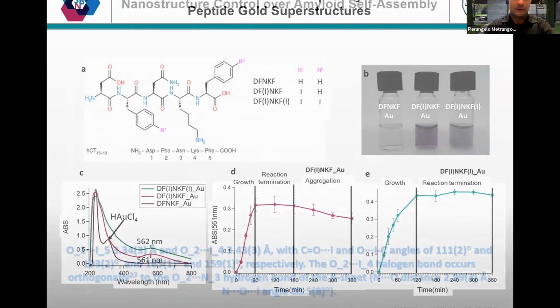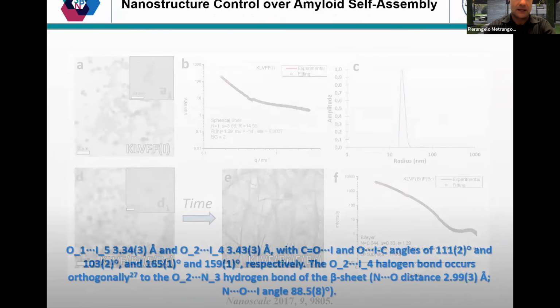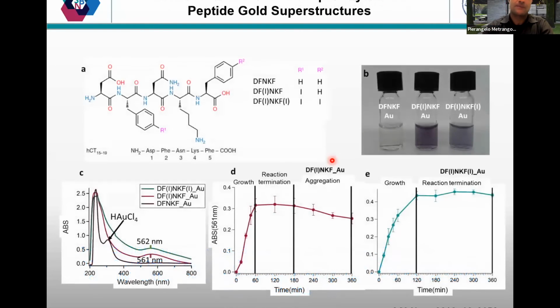Moreover, unfortunately here, for some reason, the crystal structure is not displaying, but in this paper we were lucky enough to crystallize these peptides for the first time. We could see in the high resolution single crystal structure that the halogen bonding is cross-linking the beta sheet by making orthogonal halogen bonds with the beta sheets.